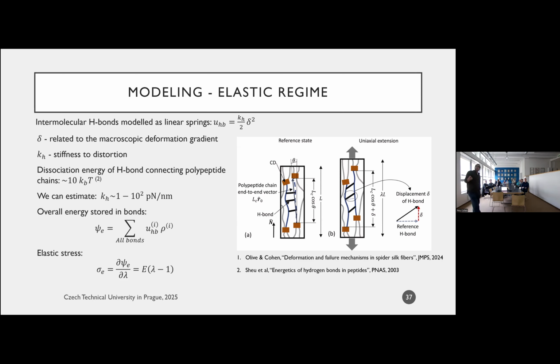And so what we've done is we said, let's model these bonds as elastic springs, as linear springs. It looks like this. Delta is the distortion, how much the bond moved. KH is what we call the stiffness to distortion. This number we estimated, since we know what the dissociation energy of intermolecular bonds is supposed to be, about 5 to 10 kT. Based off of this number, we can estimate the stiffness. There's quite a range to it, but at least it's an order of magnitude.